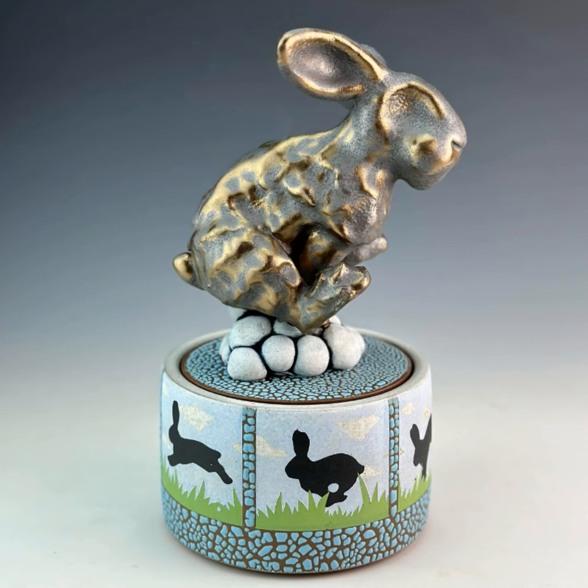Because if I touch it again, some of that reticulated glaze will fall off, and sometimes it does fall off. And luckily, it's organic enough. I think it sort of looks mossy, that if a little bit of it does come off, it's still okay with the piece. So I guess that also points out that I have to plan how my kiln load is going to be loaded in my head before I even start. I know that the bottom of my kiln's a little bit cooler, so I'll put my taller vessels in the bottom and then shorter on top, so that everything gets cooked nicely. And then usually when I unload my kiln, I have a little bit of chipping to do because that reticulated glaze falls off. But it's a labor of love.